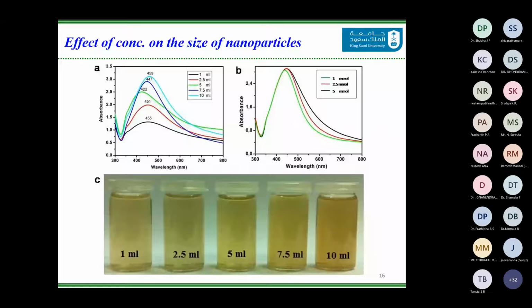So if you can see, in the case of 1 to 5 ml of plant extract, the nanoparticles are slightly smaller in size. However, when you increase the concentration further, the lambda max shifts from 422 nanometers to 459 nanometers, which indicates that the particle size is slightly increasing.